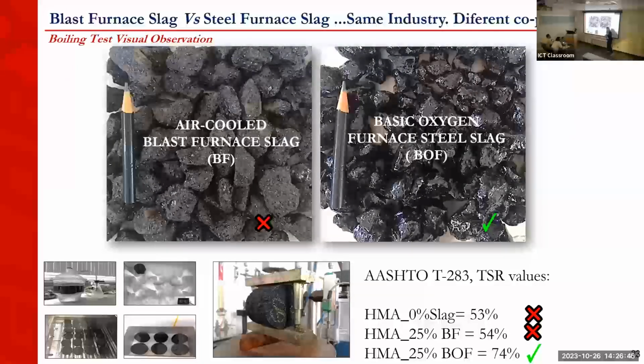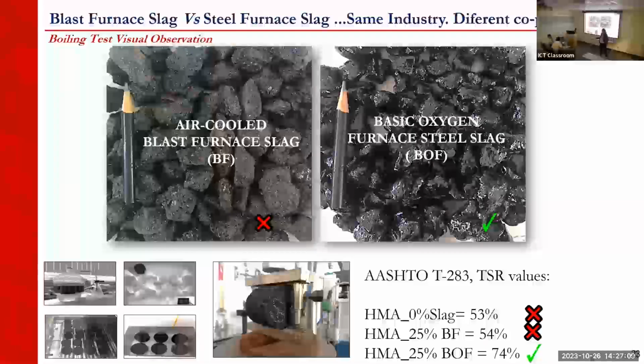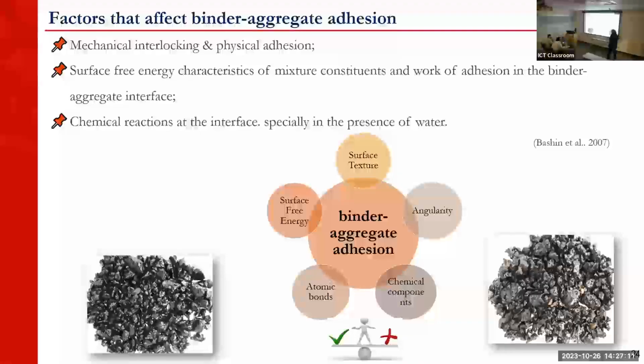When we replace natural aggregates by BOF, the moisture damage resistance increased compared with our reference mixture. This was expected because we knew this slag had a better adhesion. But you want to know why this slag has a better adhesion than this one? They come from the same industry. What is happening? Check that.